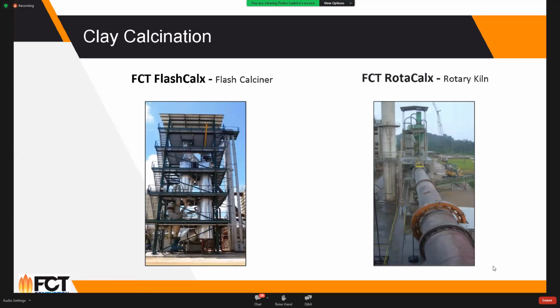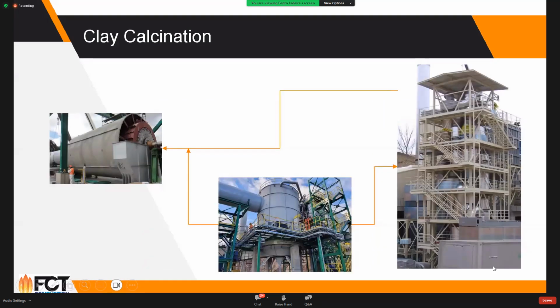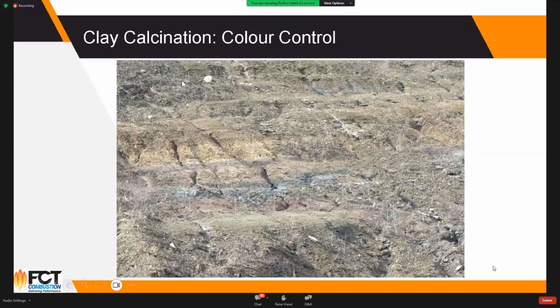Well, FCT has two technologies for clay activation, one being the flash calciner and the other one being the rotary kiln. We don't prefer one over the other. We just look case by case at which one is the best fit for your process. Different configurations, you can run the preheater or the flash calciner with a hot gas generator, and then you have a dryer. You have to dry the clay before entering the tower. So finally, we can use very flexible combustion systems like hot gas generators, and you can introduce a lot of biomass, alternative fuels, and even coarse fuels.